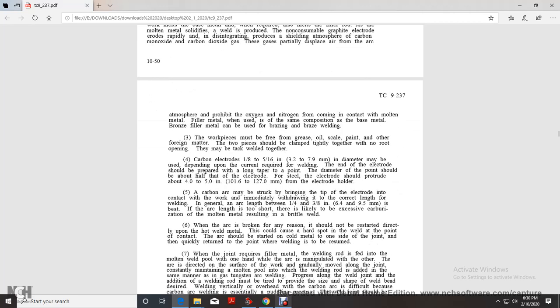Carbon electrodes 1/8 of an inch to 5/16 of an inch in diameter may be used, depending upon the current required for the welding. The end of the electrode should be prepared with a long taper. The diameter of the point should be one half of the electrode diameter. For steel, the electrode should protrude 4 to 5 inches from the electrode holder.